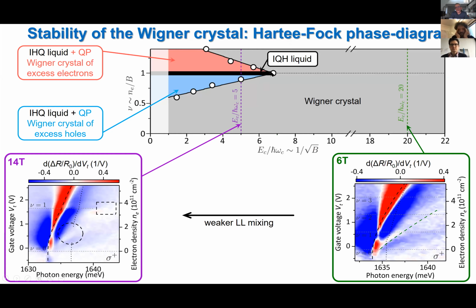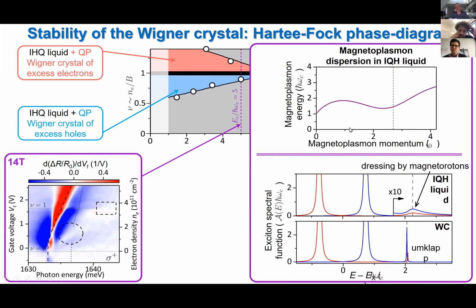And this resonance at nu equals 1, we believe, is due to the fact that now we have an integer quantum Hall state, which has softened magnetorotons. And it is these magnetorotons that also lead to broad features in optical spectroscopy. These are different than umklapp. So umklapp in an ideal system without disorder, which of course doesn't exist, would lead to delta function resonances, whereas the dressing of excitons by magnetorotons would result in broad resonances due to Van Hove singularities at the roton minimum.